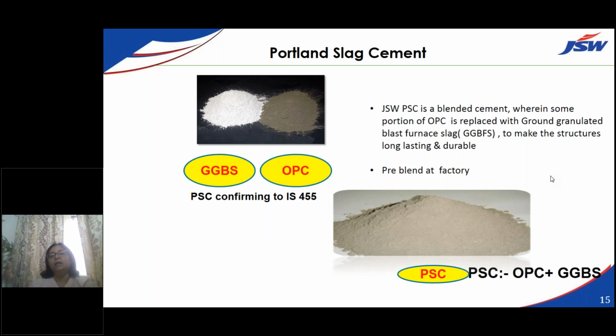If you see EN, British codes or European codes, in EN codes the slag goes up to 90% also. Places where there is a lot of marine environment, cold weather is also there. But however, even in EN and also in IS, the slag replacement percentage is very, very much on the higher side, but the fly ash can go up to maximum 35% because of the different sources of fly ash